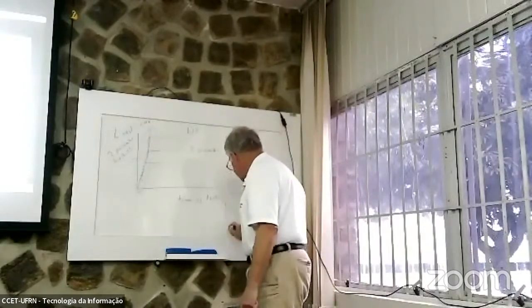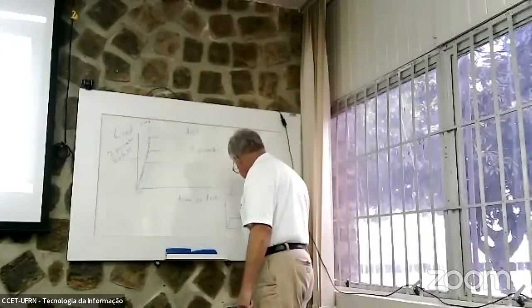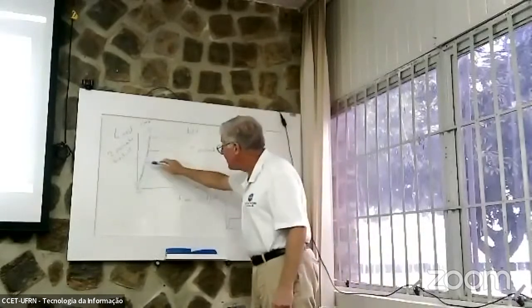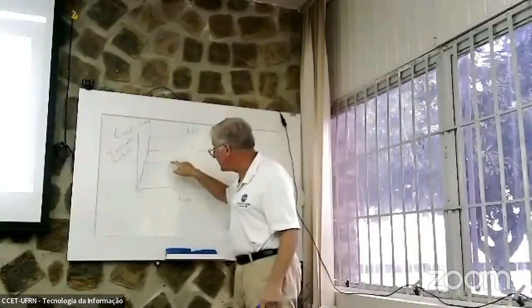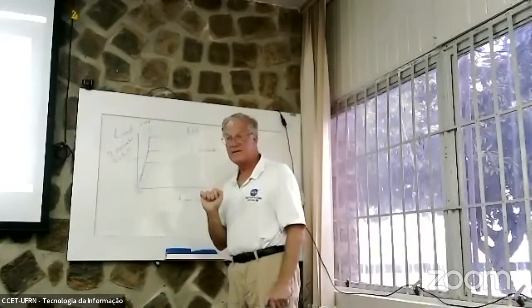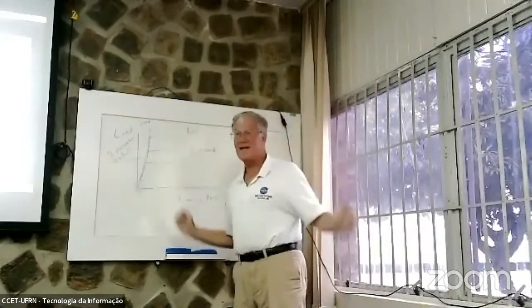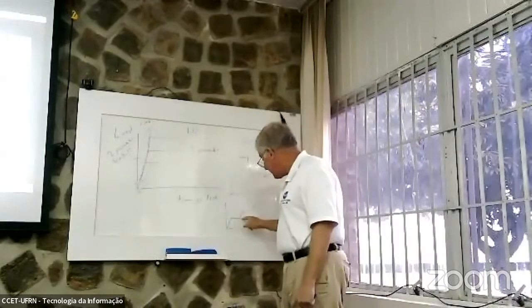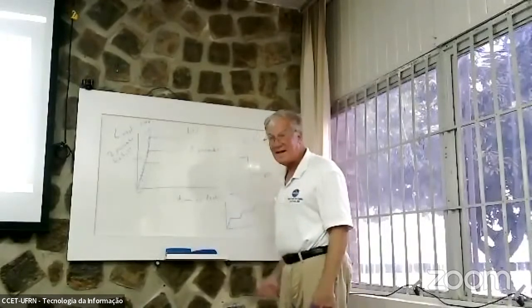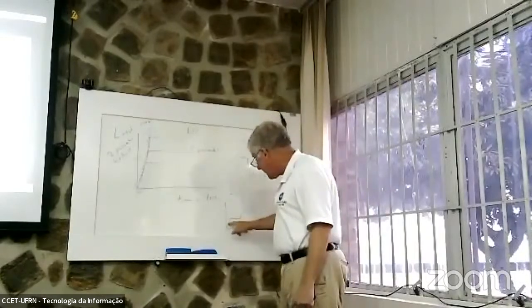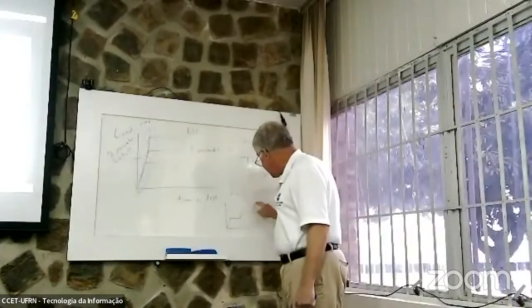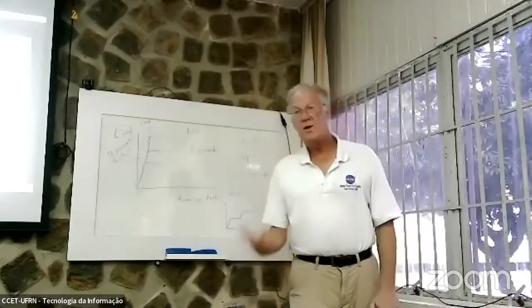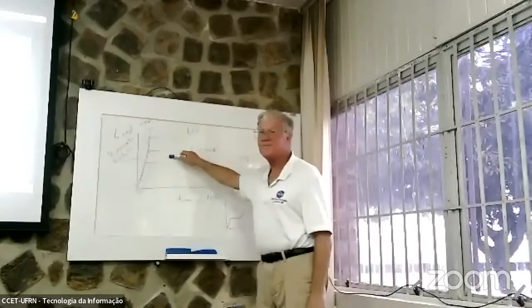And then we're going to do what are called step tests. So in a step test, really, on this test, when we allocated the test items, we said it's either going to be this load, or this load. That requires a lot of test loads, a lot of test items, expensive. Well, it'd be cheaper if I could just run it up the ramp. So this item, and then this level, this level, this level. I started out with like 100 test items, and so many fail here, so many fail here. Interesting, nothing fails here, nothing fails here, some fail here, some fail here, and then we censor it. Question is, does it give us the same results as this?